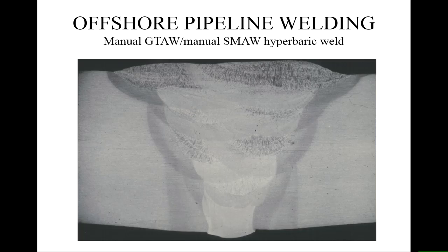So here's a hyperbaric weld. It's been done manually, so it's got a V preparation rather than the tighter U preparations that you'd see for the automatic welds. But it doesn't look much different from a conventional weld done at atmospheric pressure. So the actual weld metal freezing and microstructures you get are very similar. It's more to do with the skill of the welder and the welder being affected by the pressure rather than the actual intrinsic welding process.